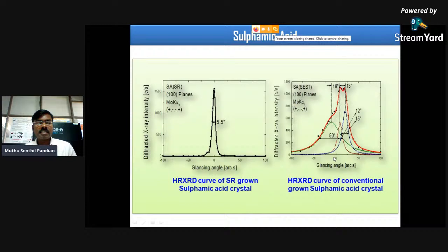So to identify the crystalline perfection of the grown crystal, high resolution X-ray diffraction measurement was performed under identical thickness. This is for conventional method and this is for SR method. For good quality single crystal, the FWHM, full width at half maximum, of the grown crystal must be a single and sharp peak. So this is for SR method, the single and the sharp peak. But in the case of conventional method, there are a lot of grain boundaries. So the entrapment of solvent molecules into the crystalline matrix is responsible for observing this kind of low-angle grain boundaries.